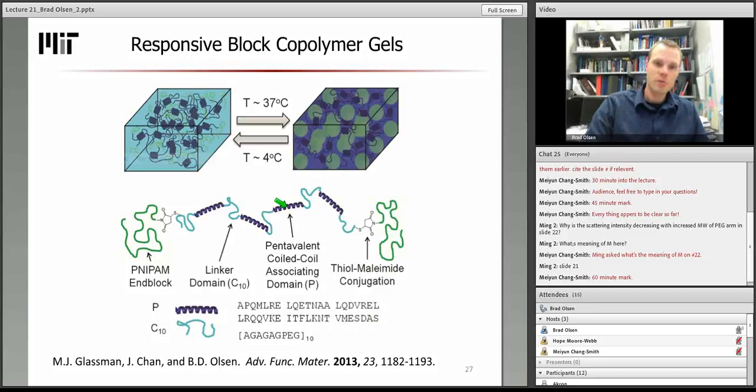Now, following the work of many talented researchers before us, we apply a Percus-Yevick disordered hard sphere model in order to try to capture this self-assembly behavior in the block copolymer gel. In most of these copolymer gels, the copolymer nanodomains, unlike some of the examples shown to you by Professor Lodge, don't order onto a regular lattice.